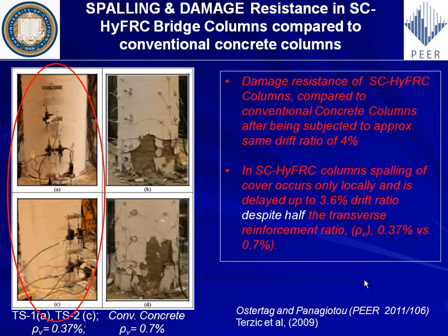In regards to spalling and damage resistance, what you see here on the left-hand side, what I circled in red, these are our high-performance fiber-reinforced composite columns. So these are the self-consolidated. On the right-hand side, you see the same size of columns, but they contain the conventional concrete. At a similar drift ratio of around 4%, you can see that we have much less damage in the hybrid fiber reinforced composite compared to the control specimen right here. The control specimen here was tested by Terzic et al.. And what I want to emphasize here is that this kind of enhancement in damage was obtained despite the fact that we used only half of the transverse reinforcing ratio. So the conventional one has 0.7%, ours has 0.37% as a transverse reinforcing ratio.